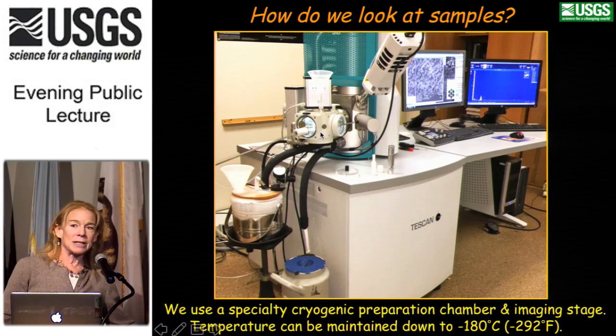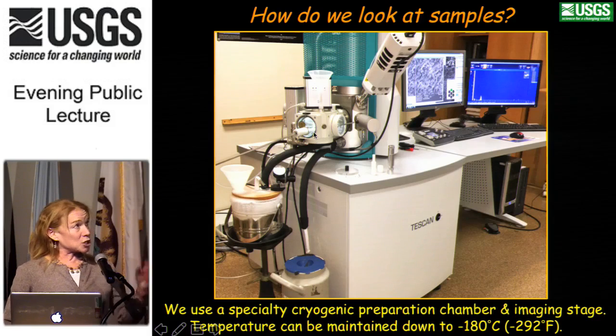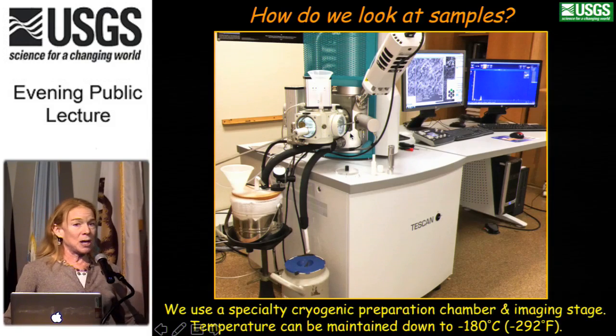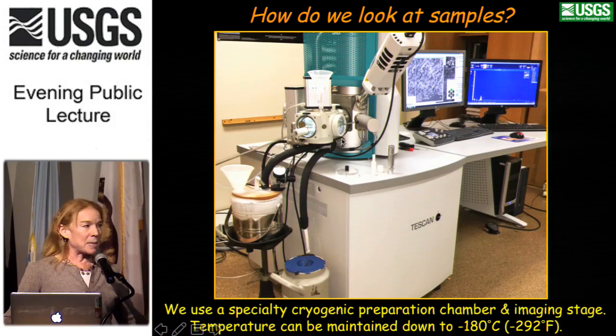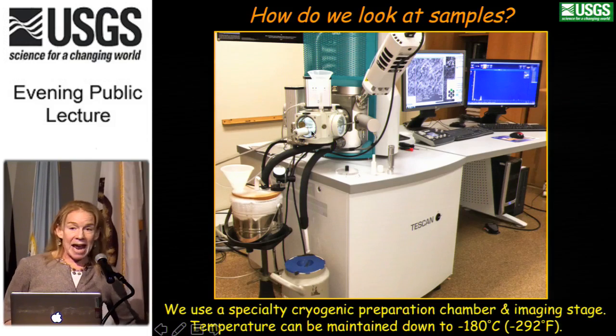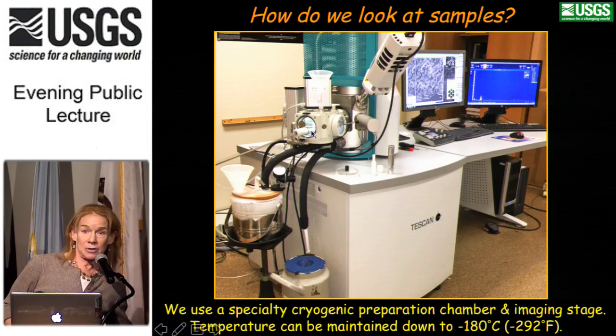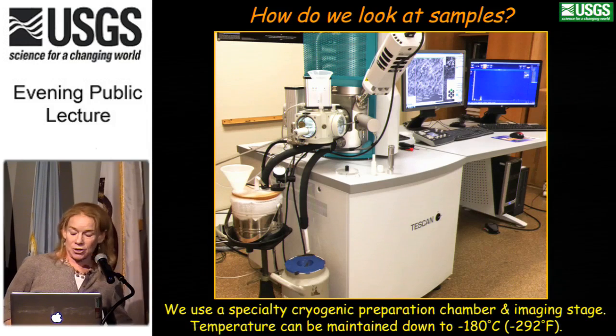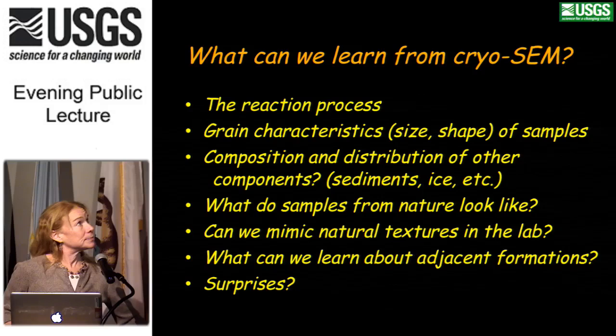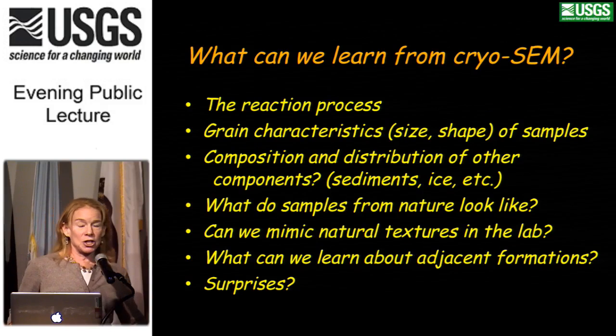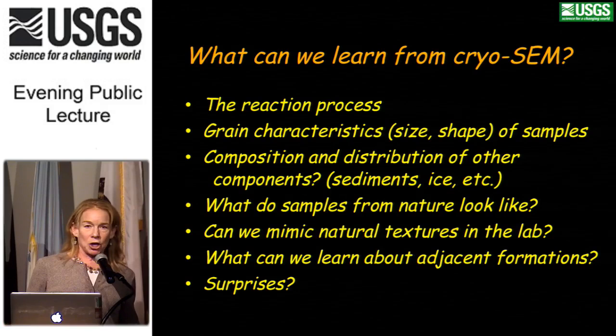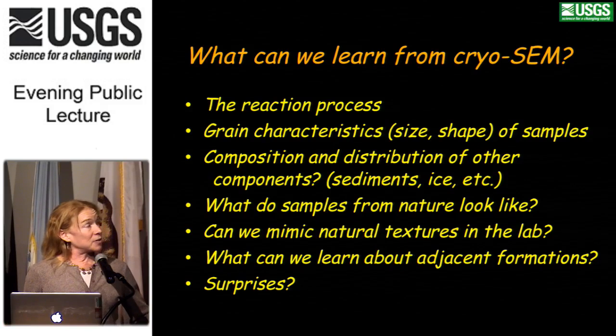I take my samples out of liquid nitrogen. I take a small piece, put it into the preparation chamber, cleave off a fresh fracture that's clean of condensation, and we put it straight into the SEM column where we can maintain temperatures down to minus 180 centigrade, which is minus 292 Fahrenheit, just for scale. At those temperatures, we can hold the hydrate stable for quite a while, depending on the vacuum conditions. We started doing cryo-SEM in the early 2000s.